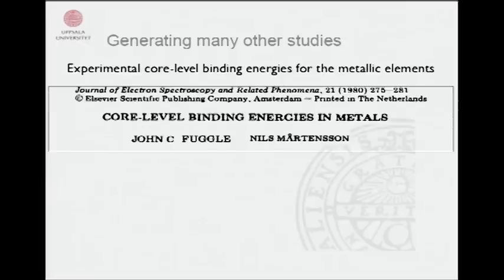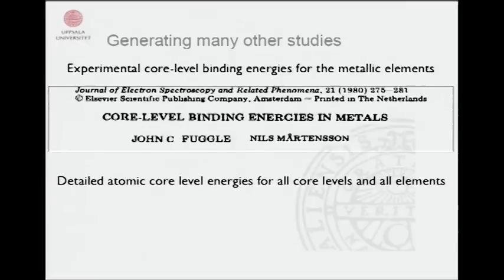First of all, the metallic elements were not carefully measured. We could all of a sudden see this, and made this compilation, for instance, together with John Fuggle, which is something that is very much used also, where we had experiments from many labs, but not least from our lab. And then we also had a method to derive, experimentally or quasi-experimentally, you could say, by combining data, atomic core level energies for all core levels and all elements.